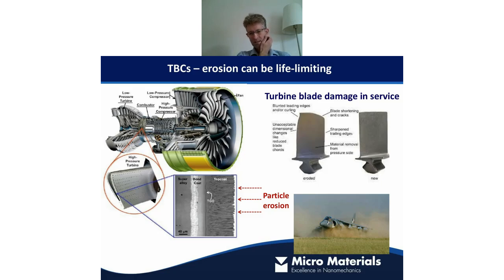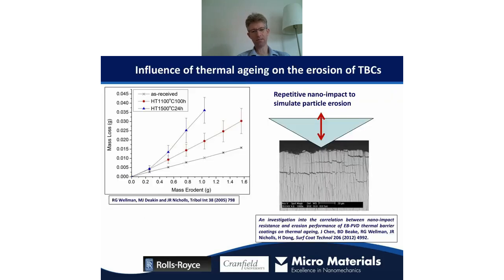So the manufacturers of these coatings really want to try and optimize their thermal properties with their erosion performance. And in a jet engine, obviously these things are susceptible to very high temperatures. They're in a very high temperature environment. So this is not a nano impact test result. This is an example from Rolls-Royce, where they're looking at individual erosion tests. They're looking at doing an erosion test and taking the coated part out and measuring it and putting it back in and continuing the erosion test. So it's a very time-consuming process.